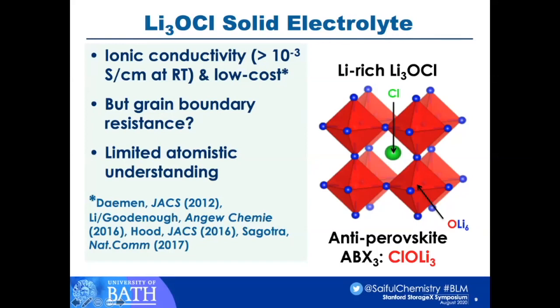The perovskite structure is, I'm sure, well known to most of you, if not all of you. What I find fascinating about this structure is the antiperovskite. So here, the center of the octahedra is occupied by oxygen. The corners of that octahedron are now the lithium, the cations, and right at the center, the A site, is the large halide, the chloride ion. So that's why it's an antiperovskite. So in ABX3 formula, it's ClOLi3.